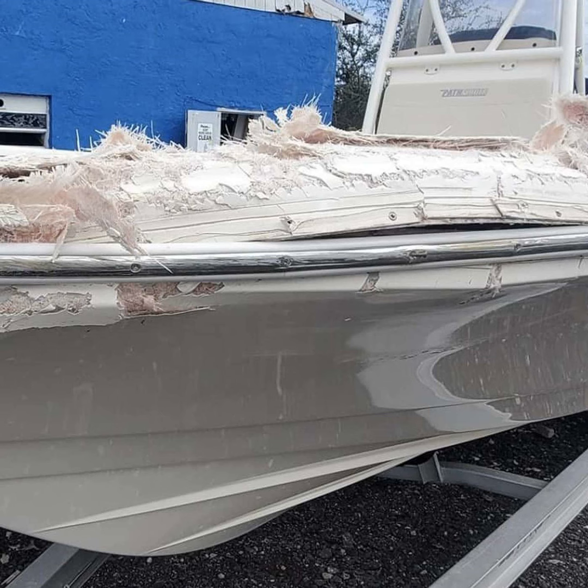So when you're grinding, if you were to grind the gel coat off good fiberglass, then what you would see under there is kind of going to look like maple syrup color, and it's going to be uniform in color, and you're going to be able to see the fibers within the fiberglass, especially if you pour some acetone over it or even water. When you start seeing white fiberglass, that is damaged or delaminated fiberglass or crushed fiberglass.